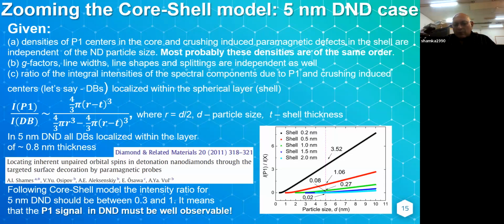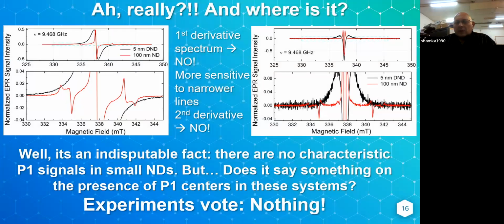Well, observable. But what happens in experiments? We can compare the 5 nanometer diamond spectrum with the 100 nanometer nanodiamond spectrum. What can one see? Nothing in the spectrum of the small nanodiamonds, not ratio 1, not ratio 0.3, not even ratio 0.03, nothing. This signal is not observed in 5 nanometer nanodiamonds. It means that the pure core shell model practically doesn't work here.